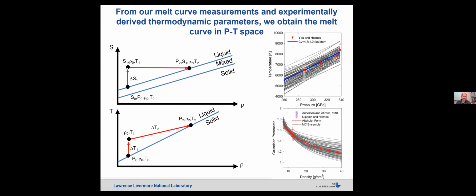You first isochorically heat that material to a higher entropy point, which requires the isochoric heat capacity to understand the increase in temperature. And then you isentropically compress that material to a higher pressure state along the liquidus, right? So these are the two steps. And the real question is, okay, what is the change in temperature as you follow these two steps? And that will then give you the melting curve in the pressure-temperature plane.